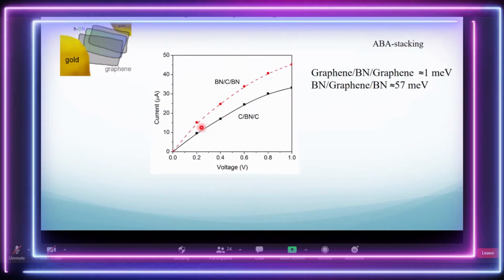So we do the same thing: take the DFT density, feed it into this Green's function approach, and calculate the IV currents. And if you look at this graph, you wonder, which I did when my student showed me this graph, that something is wrong. Because in both cases, whether the graphene is in between or boron nitride is sandwiched, the current is more or less the same. And you see here, the gap is different. So something is not making sense.